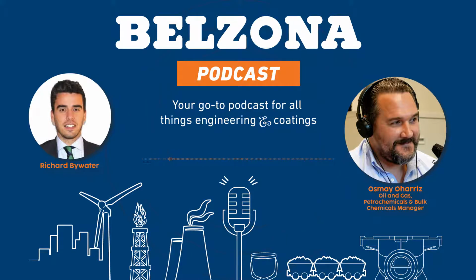Yeah. Well, there's several. I think the ones that are mostly known are an upgrade to the metallurgy that you're using, cathodic protection, and the use of different coatings just to line the inside of this vessel. Okay. In a nutshell, because we could be talking about each one of these categories for hours, when you have a metallurgy update, you're pretty much using corrosion-resistant alloys. So think of stainless steel, for example. You can have nickel, you can have several different clads that you combine with carbon steel. So you use carbon steel for, let's say, the least critical sections, and then you use these corrosion resistant alloys for the most critical ones, the ones that are prone to corrosion.